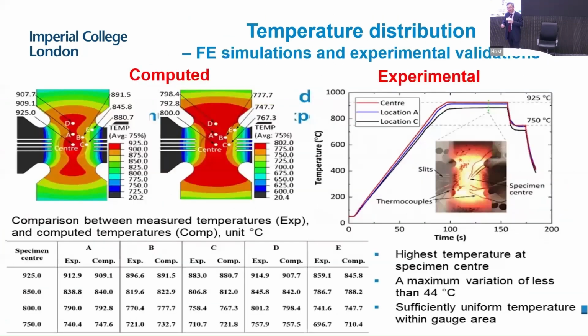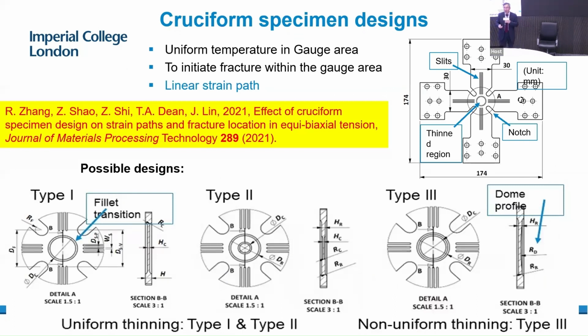There are a few parts we need to consider for this, and one is the specimen design. For this specimen design, we need to consider a few criteria. One is that in the gauge area, in the middle, we want uniform temperature, as uniform as possible. Another is that for the strains, we would like to have fairly uniform strains in the gauge area. And also, we want failure to initiate and occur in the center area.